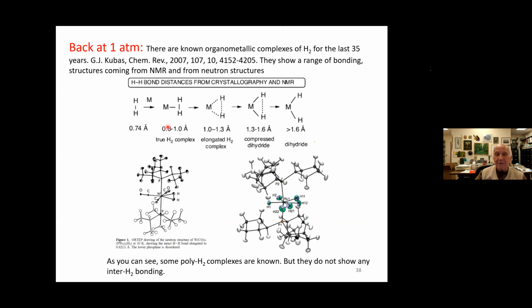They were first made 35 years ago, and in these, remember, H2 is H2. It appears in a gas, it appears in a molecule, it appears as a solid at various pressures. You're not going to make something else out of it. So you better pay attention to it when you see it in a molecule. And that's what the high pressure community did not do for these complexes. Because the distances here are available, because most of those 500 structures have had neutron structures. And you can also get a distance from NMR coupling constants.